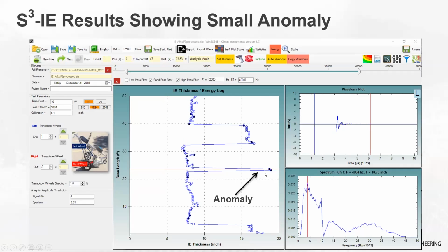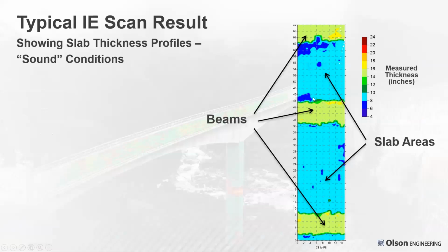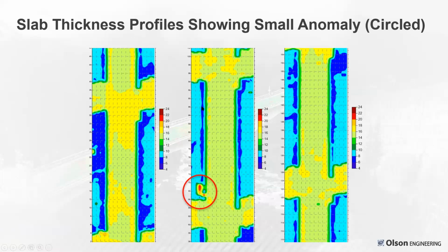So we took all of these results from multiple scans and plotted them up. This is a single area of the slab showing beams, these green areas up here at 14 to 16 inches, slabs, the blue areas at around 8 inches, 7 to 8 inches. So this is a sound zone of the overall slab. Here's some additional slab profiles, and here you can see crossing beams, beams going in both directions.